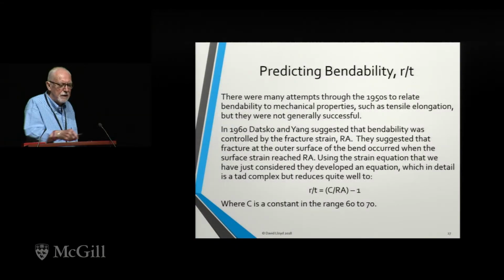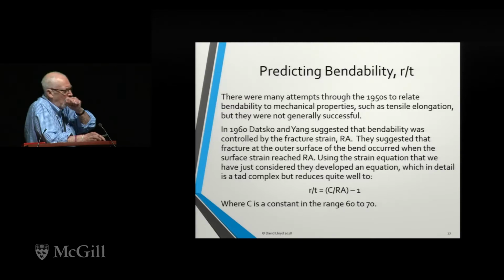In fact, if you actually look at the paper, the analysis is a tad more complicated than that, but that empirical equation actually is really very close to the theoretical expression that they developed. So there's this very simple equation. This is the bend radius that you can get where cracking occurs. This is the thickness. This is the fracture strain, and this is a constant. And that constant for a moving neutral axis is in the range 60 to 70, at least in the aluminum alloys that we've looked at. So it's 60 to 70.